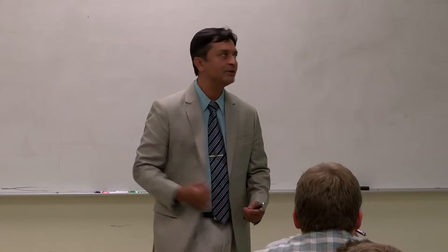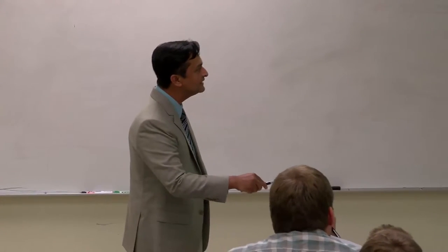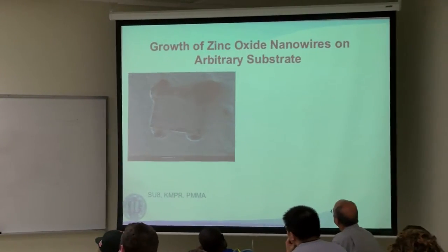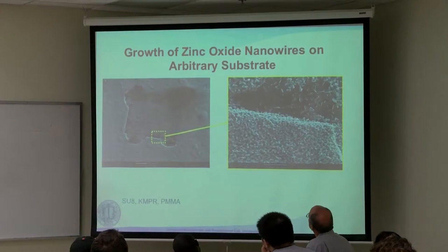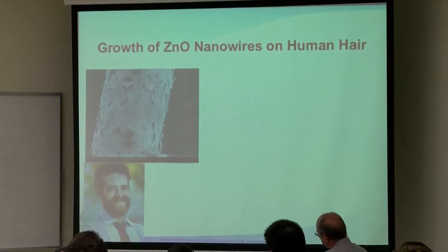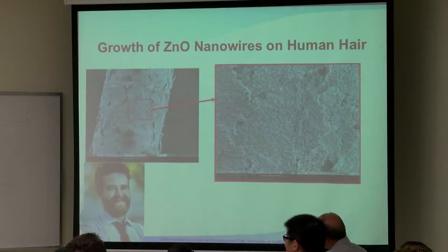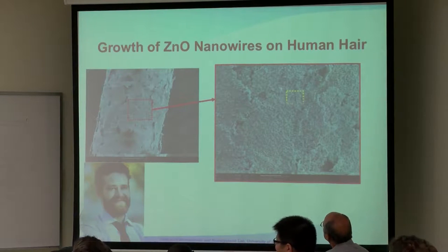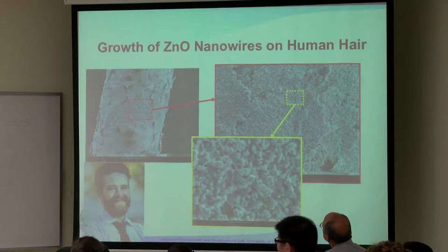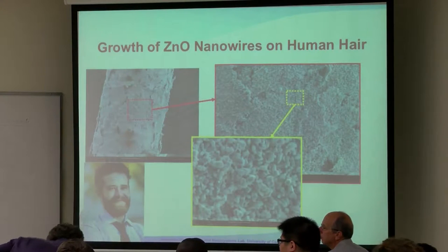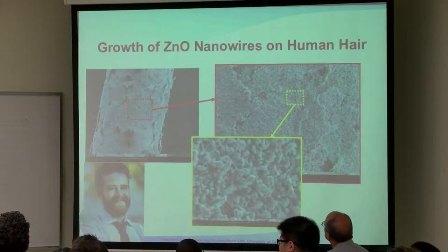Because nanostructures are small, really tiny, you can grow them on anything. We showed in our group that we can grow them on textiles. Here you're looking at nanowires grown on glass substrate — we coated them with other material, turned them into solar cells, and they work for harvesting energy. We grew them on plastic substrate, on polymer, on cotton thread. We even grew on human hair — one of my students grew nanowires on human hair to harvest energy. These materials on any substrate are as good as single-crystalline semiconductor material used for CMOS fabrication.